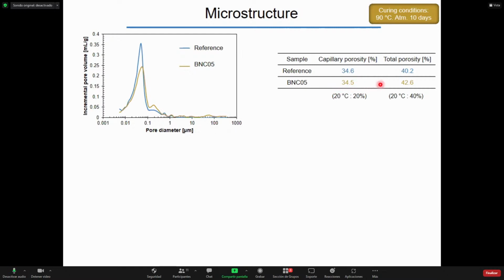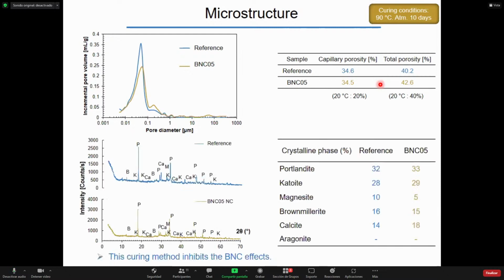In this case, the bacterial nanocellulose did not show any improvement in capillary porosity. It did not reduce capillary porosity, and neither in the X-ray diffraction test did we see any change in the crystalline phases, having similar components as the reference samples. This means that this curing method inhibits the bacterial nanocellulose effects.